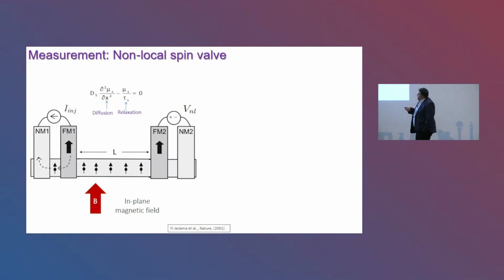This is a measurement called non-local spin valve. Basically you have four electrodes, and on the right side you are just driving the charge current, but there is no charge current propagation on the other side of the circuit. You are creating some spin accumulation by passing the current through a ferromagnet. These spins, of course, diffuse to the right side, but also to the left side. If you place your ferromagnetic detector at a distance shorter than your spin relaxation length, you should be able to measure a signal which comes directly from the spin diffusion.